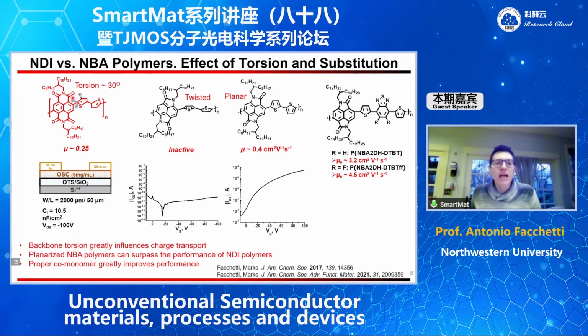So one of the things we have done is to release this torsion to make the polymer flat. And from the molecular design, making it flat should make a better polymer. And one way we made it flat is by removing 2 carbonyls. If you remove these 2 carbonyls here, you end up with this polymer. If you remove these 2 carbonyls here, you end up with the second polymer.